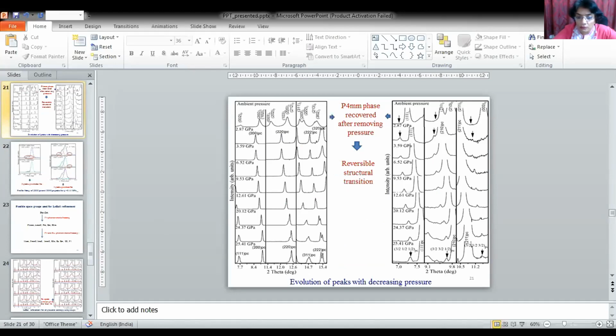No. So, Pragya, you had discussed the controversies regarding the perovskite work in one of your slides. Yes, ma'am. How does your experiment resolve the controversy? Ma'am, the first picture is MPB-like phase transition. It means from the tetragonal phase of lead titanate, it transforms to a monoclinic phase, which permits the rotation of ferroelectric polarization. While the second picture says that the tetragonal phase goes to I4CM phase, which involves only AFD transition. There is no MPB-like polarization rotation possible in this space group.